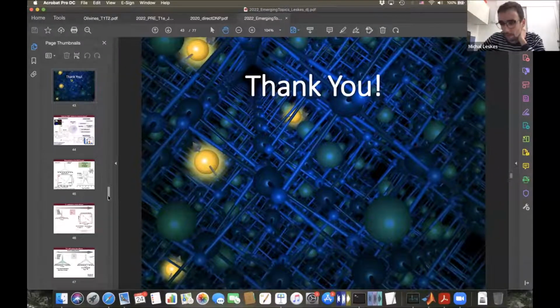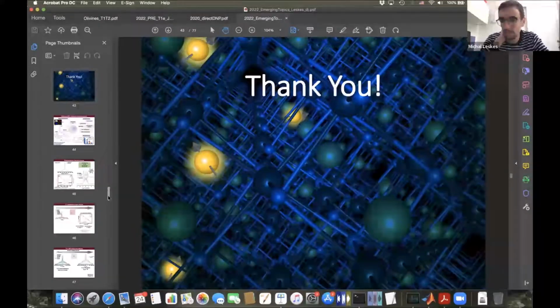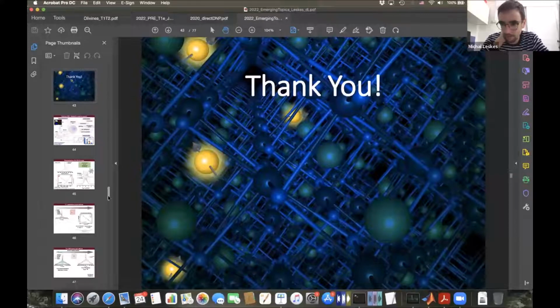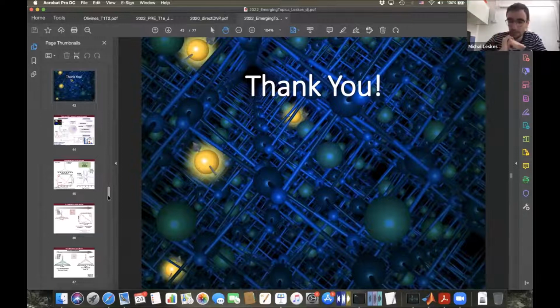Yeah, absolutely. Well, actually, we never turn the microwave off. We're continuously irradiating, but it's still true that the relaxation time depends strongly on the distance. But we always measure the relaxation behavior, and we get this very pronounced stretched exponential recovery curve. This is what you would expect from paramagnetic relaxation in the absence of spin diffusion, because you have a distribution of distances, which gives you a distribution of relaxation times, and if you add them all up, they turn out to behave like a stretched exponential. So there are nuclei where, if we wanted to wait for, let's say, 99% recovery, that would be prohibitively long times in some cases.